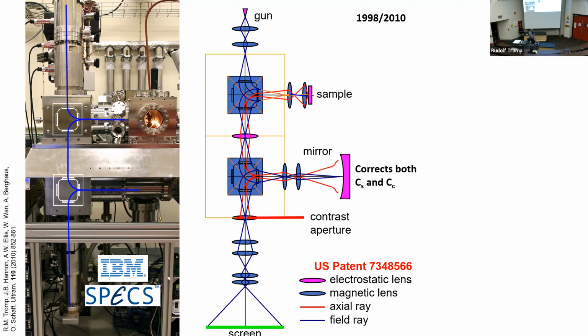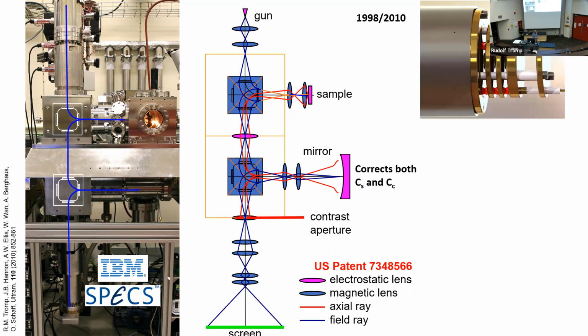A couple of years later, we added the second piece of optics here, a second deflection system plus an electron mirror. And the electron mirror allowed us to correct the spherical and chromatic aberrations of the objective lens. So without this piece of optics, the resolution using a cold field emitter is about 4 nanometers. And using this electron mirror, which you see is actually a very simple element.